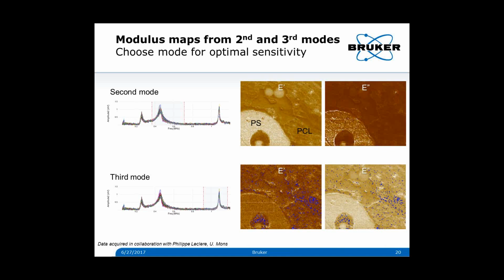Additionally, the moduli are a function of frequency, so a choice of one eigenmode or another gives a map of the moduli at whatever frequency the peak is showing up at. In the second mode, you have nice contrast of both storage and loss modulus. In the third, it's a little less contrast, it's less sensitive. We also see some blue dots here. These are identifying points where the fitting or the modulus calculation failed to converge. In addition to helping the user understand where the calculation is failing in their map, these points are excluded from further computations, allowing for more accurate statistics.